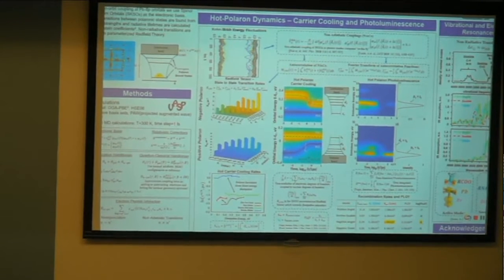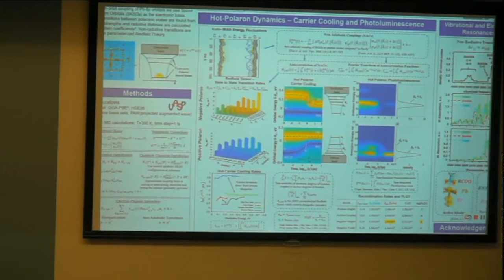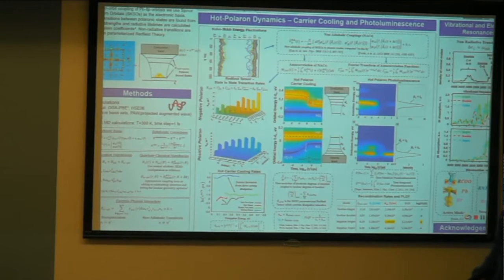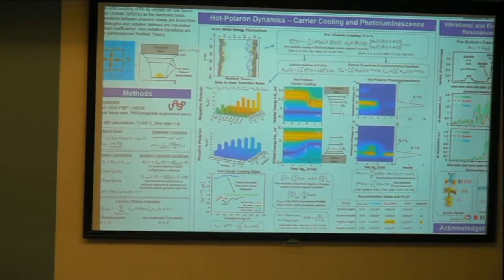What we find when we do that for all the models investigated is that the efficiency is fairly low for all the models, on the order of 10 to the negative 8 to 10 to the negative 4. And what we noticed, something interesting, is that 3 of the models showed about the same order of magnitude relaxation, or non-radiative time, but 1 showed 2 orders of magnitude slower. And each of them had about the same radiative recombination.